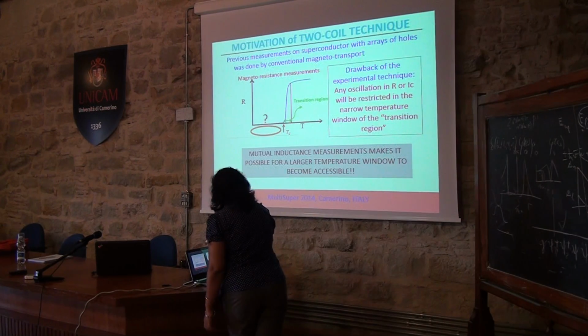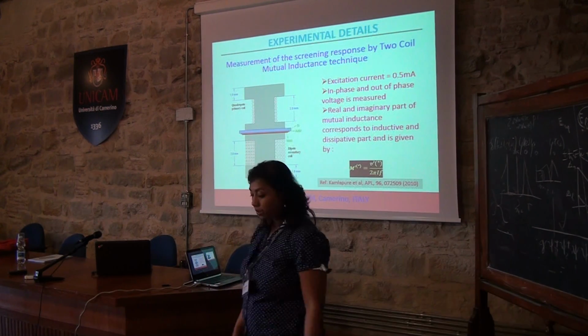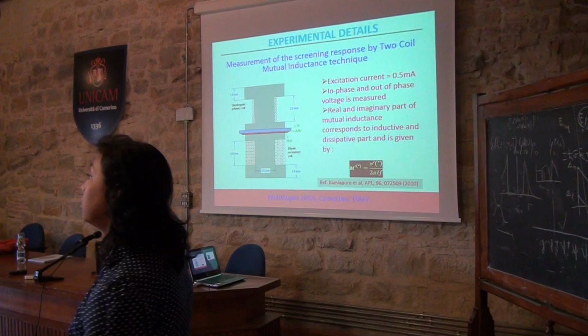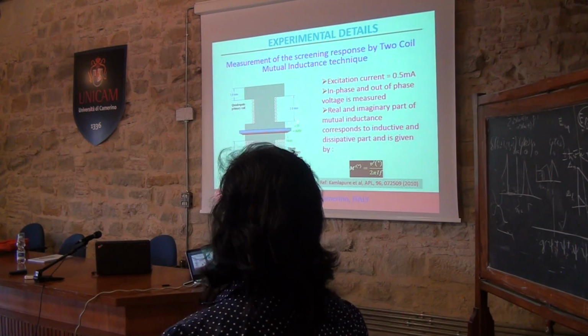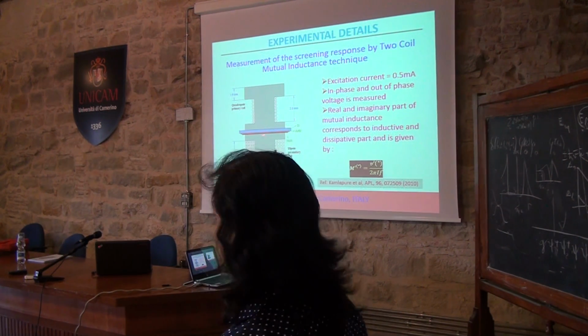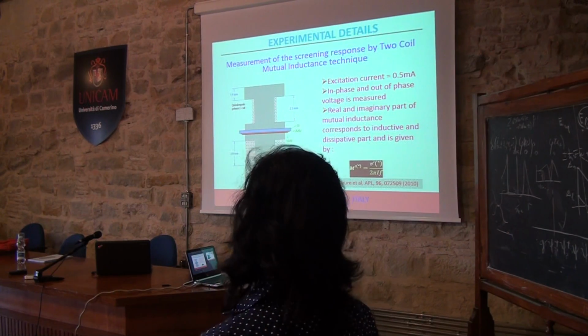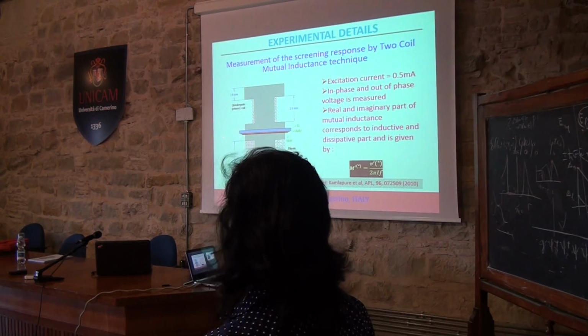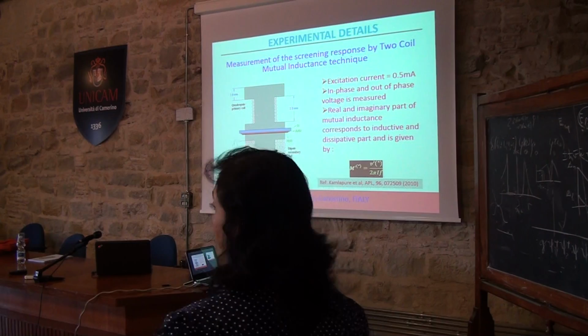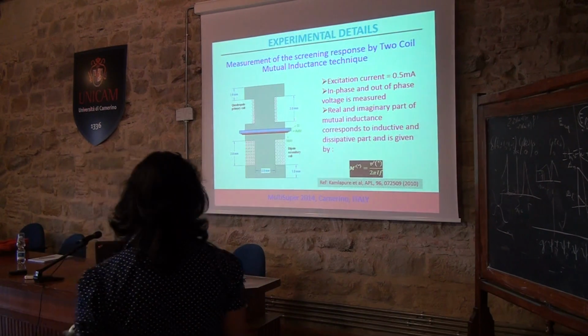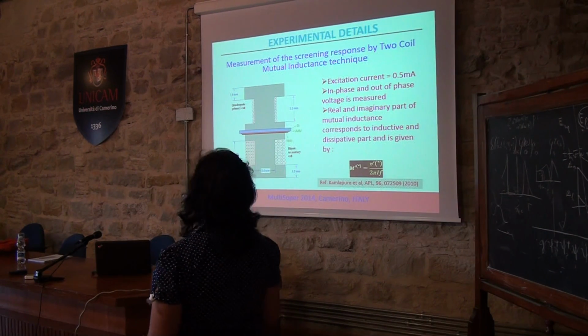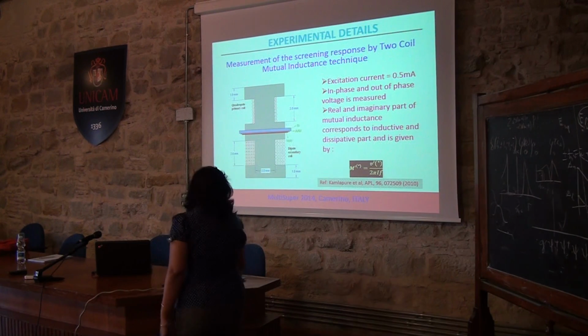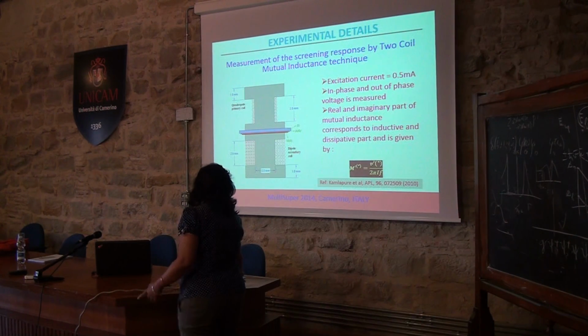So what we did is that we used a different measurement. It was based on a mutual inductance technique. You have two different coils, a primary quadrupole coil and a dipole or secondary coil, and we sandwich the film in between the two coils. As soon as the shielding currents develop, you will have a drop in the pickup response, and that is what we use to measure the screening effects.